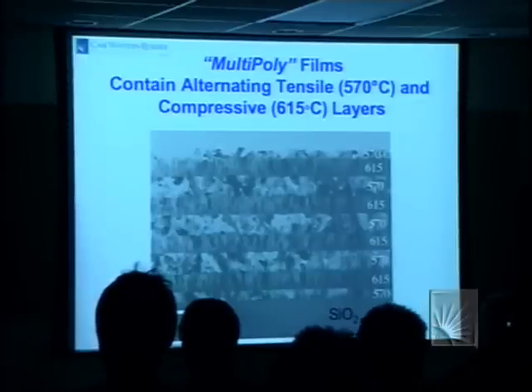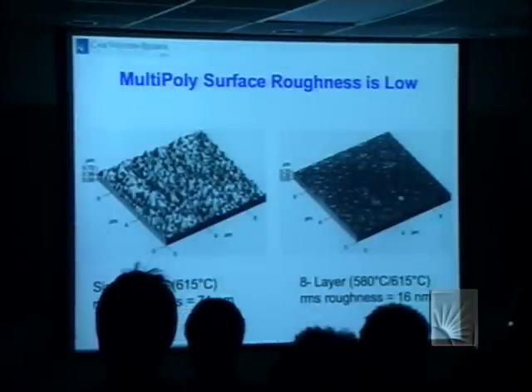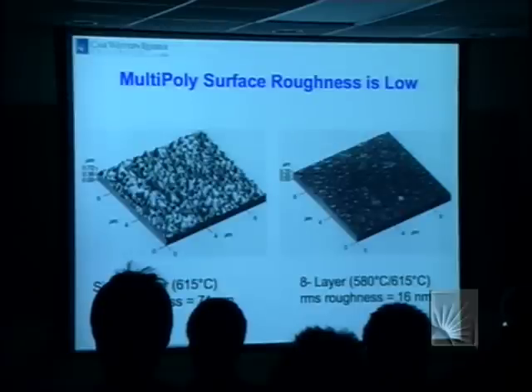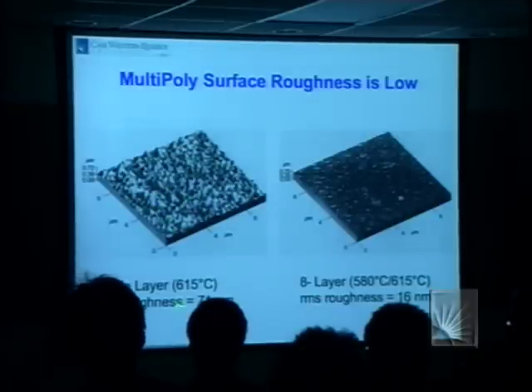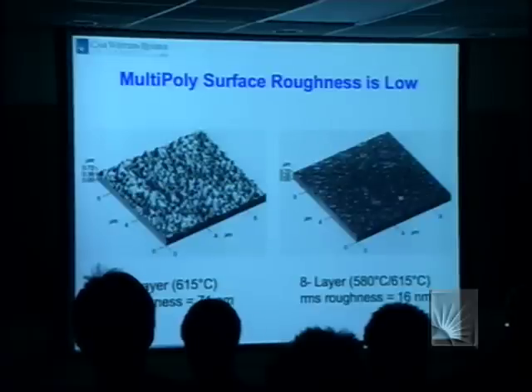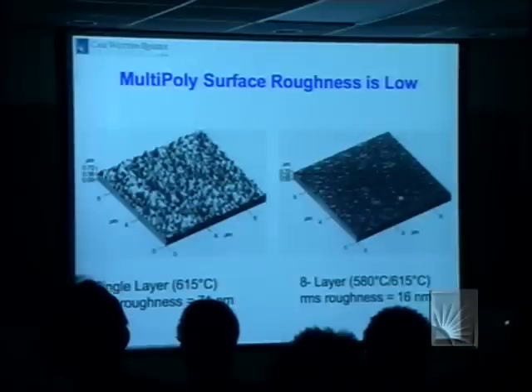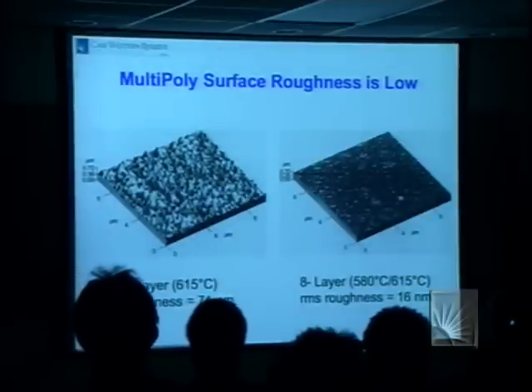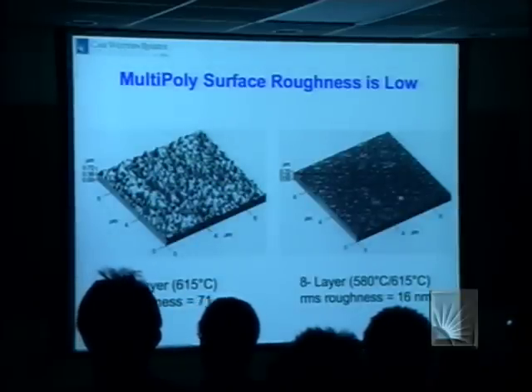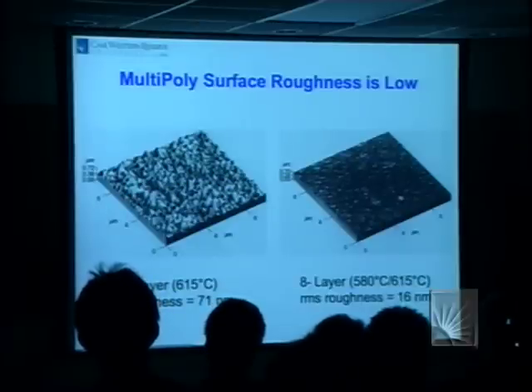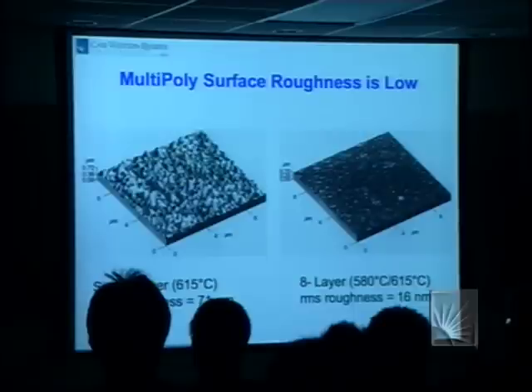And that's really neat. Because when you do that, well, let me just say one thing before I get to that. This columnar microstructure is rather rough on the scale we're talking about. The RMS roughness is 70 nanometers. And there was, when we were doing this work, a lot of interest in optical MEMS. That bubble burst with the .com failure. But at this roughness, materials are too rough for any optical MEMS devices. And so you have to go through a rather expensive planarization, and people would like to avoid it.